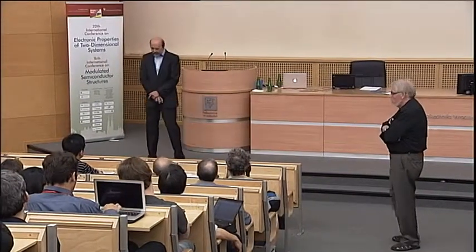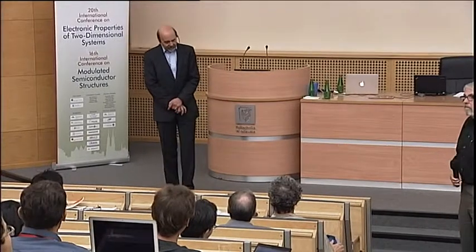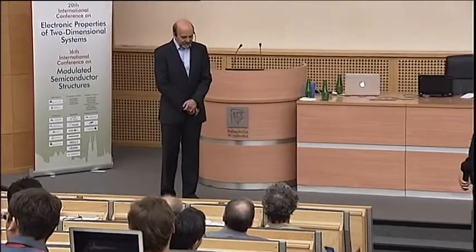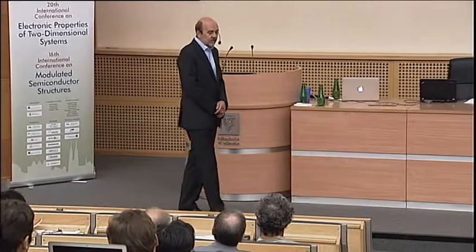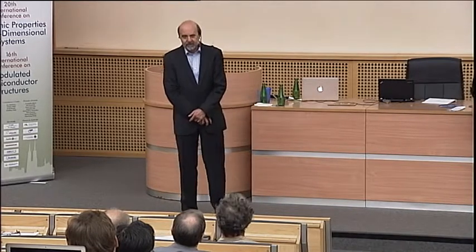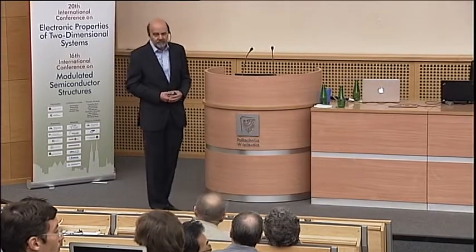There are not too many experiments performed with gates yet. Actually, we had this paper which I have shown about the quantum Hall ferromagnet studies. We had a gate, and we were able to change concentration by a factor of 3. And at this conference, Leonid Rokhinson also showed me a result, because I gave him our samples so that he can also measure. So we can control electrically, but we can also control by illumination. It is kind of similar to gallium arsenide. If we illuminate our sample, we can increase concentration a bit, but we can also increase mobility. And this is important. For the highest mobility, we also use illumination of the sample.